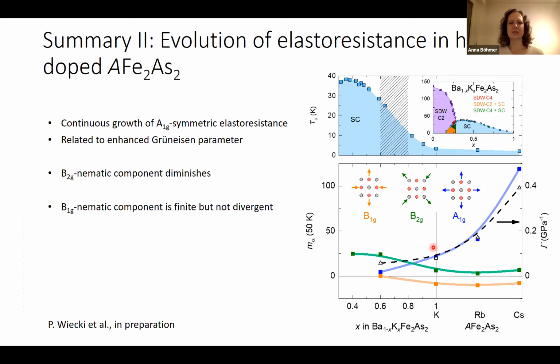So this brings me to the summary of my second part. In this evolution, we see a growth of the A1G elastoresistance systematically towards the cesium 122, which is related to the enhanced Grüneisen parameter, while the B2G simply diminishes and the B1G component is finite but never diverges.